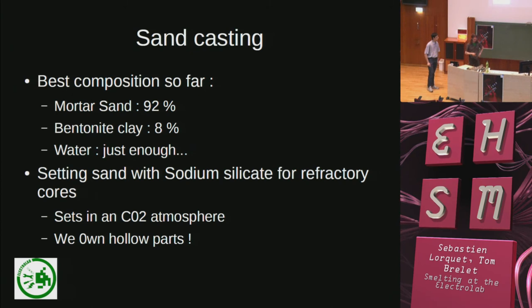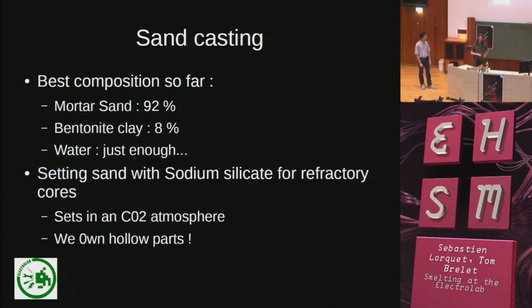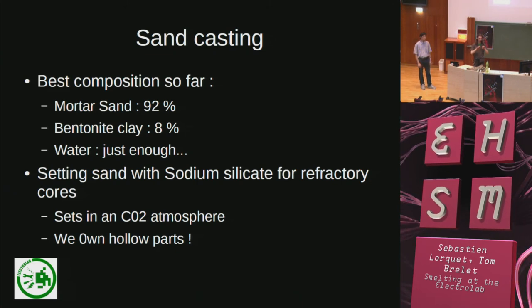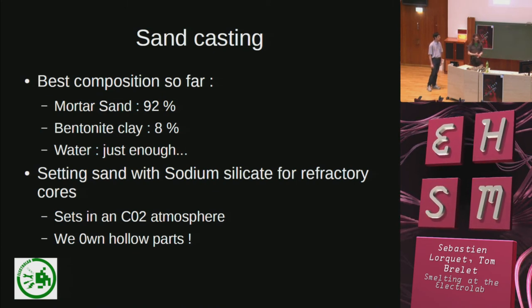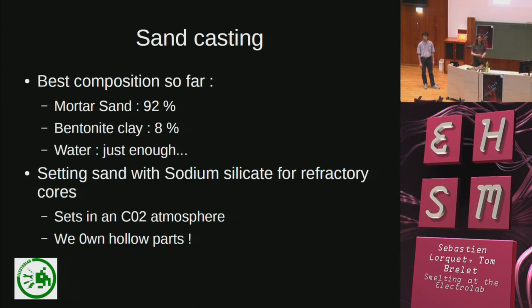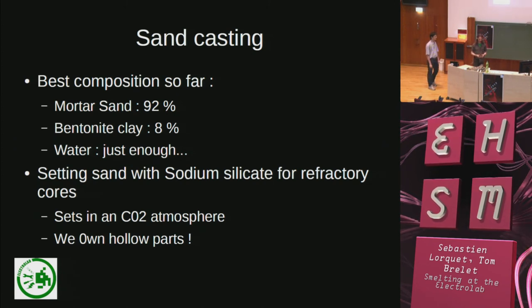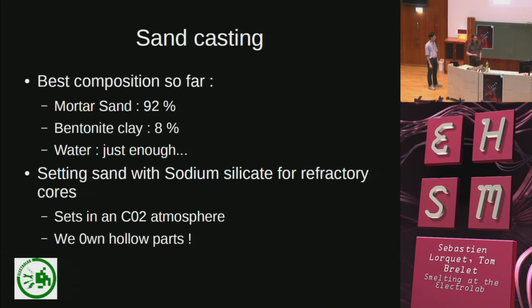We also make a chemical sand. It's useful to make cores. The core is a part you add in the mold to have a hole in the part. We found the recipe on the internet. We had sand and sodium silicate. It's a chemical compound, really difficult to find in France, especially in Paris. But we found it, and it works really well. The process is just compacting the sand in a negative mold to have the core, and adding CO2 to harden the sand, the chemical sand.